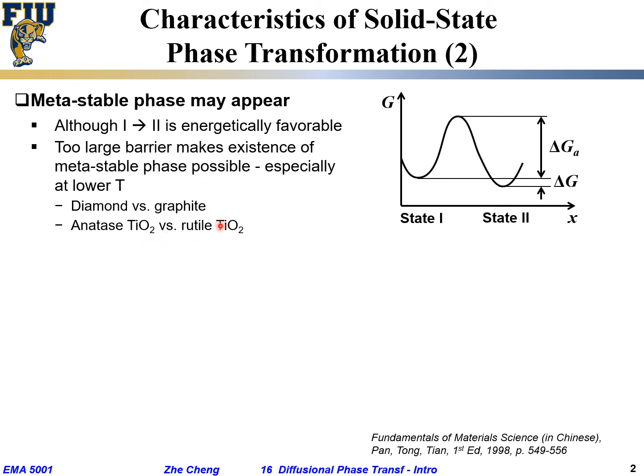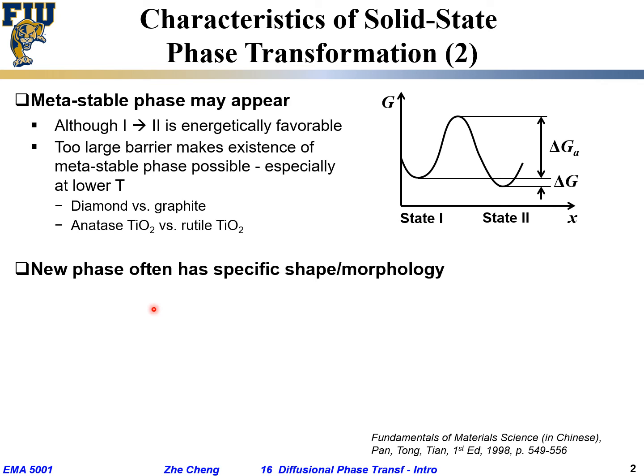Another example is anatase TiO₂ versus rutile TiO₂. Both forms of titanium dioxide have the same metal — titanium — and the same non-metal — oxygen — in a 1:2 ratio, but with different crystal structures. The anatase phase has a higher energy state compared to the rutile phase, especially at comparably low temperatures. Because of the large barrier between these two states, the produced anatase quite often stays as anatase unless heated to achieve the phase transformation to rutile.